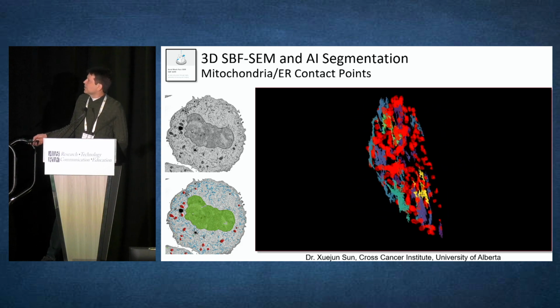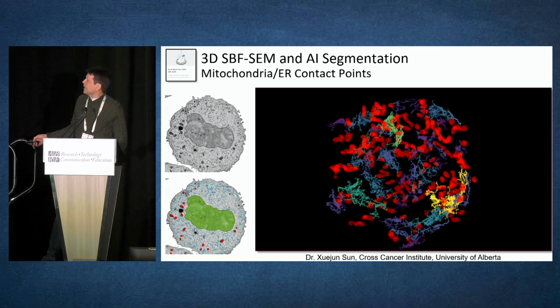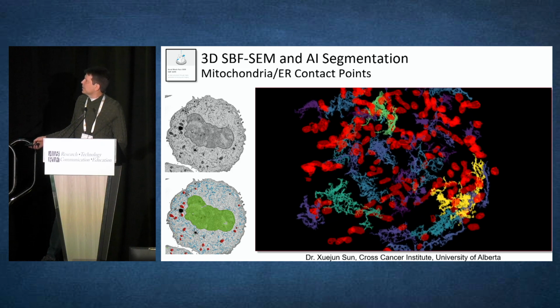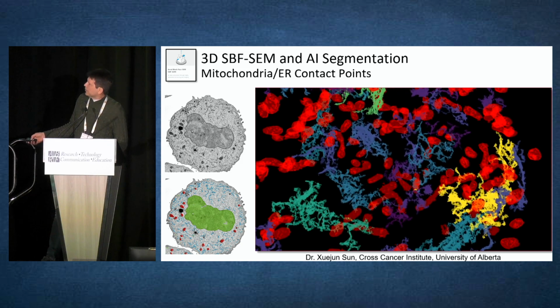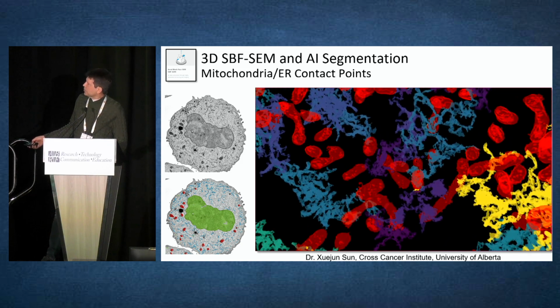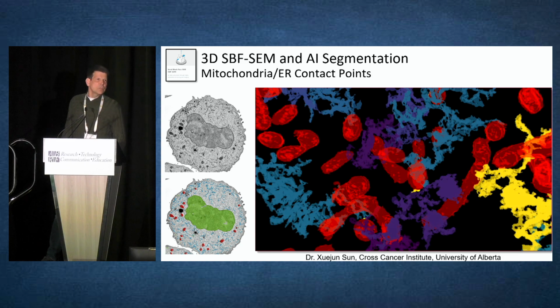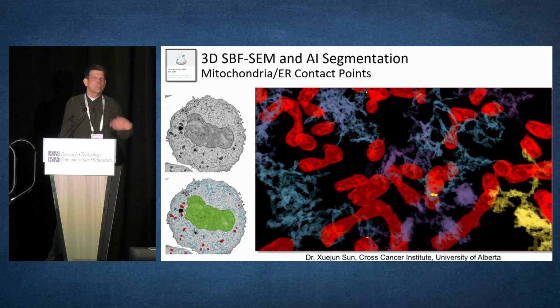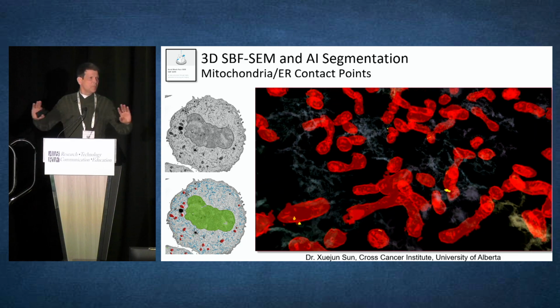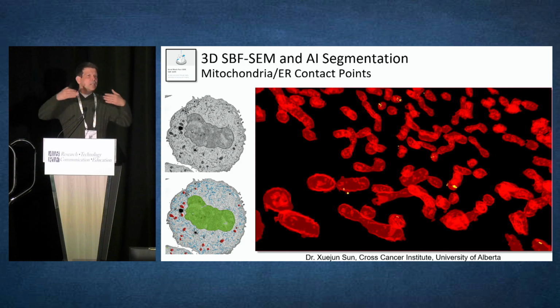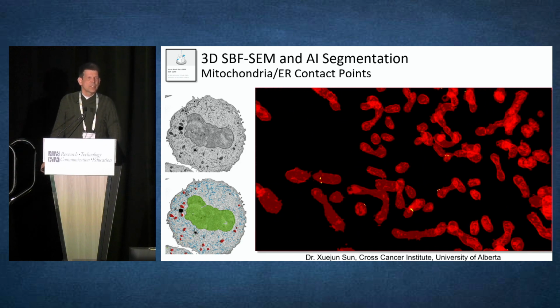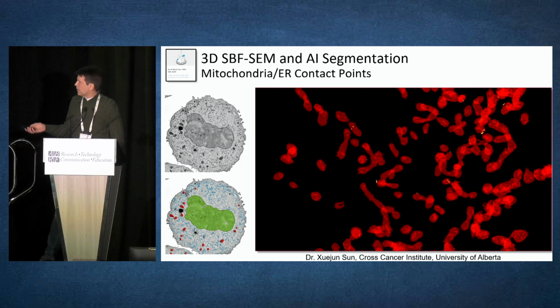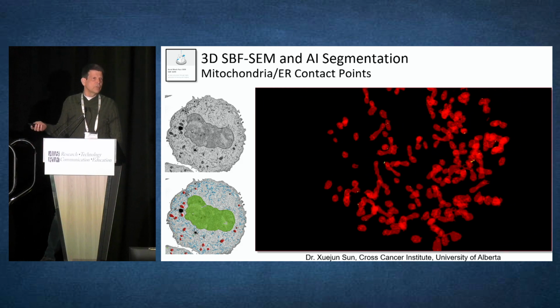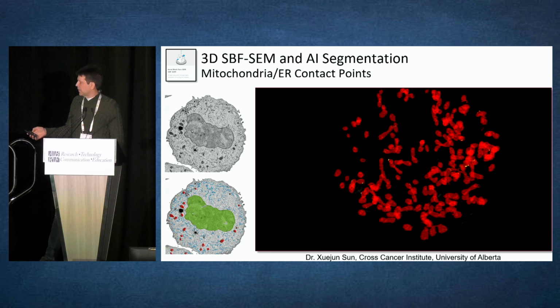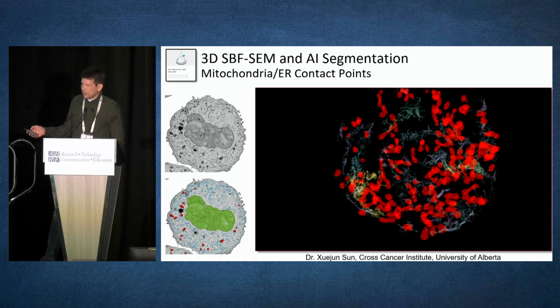Here are some cancer cells in which we wanted to look at the connection between the endoplasmic reticulum, which are all these little multicolored structures, and the mitochondria. And again, the resolution is sufficient in the volumes that we can actually find and count all those contact sites and things like this, just to give you an example. Again, you may not be looking at ER mitochondrial contact sites, but if you're trying to look at things that are in close proximity, you can use this kind of a tool. Again, that data set was collected in an overnight run using a volume electron microscopy serial block face technique, okay?